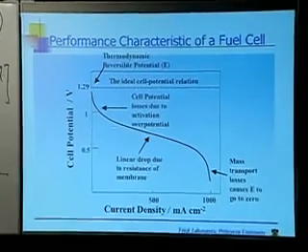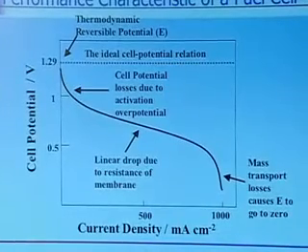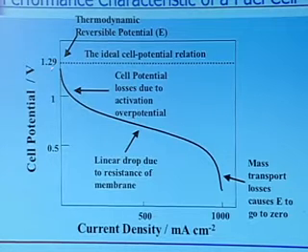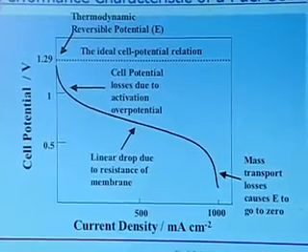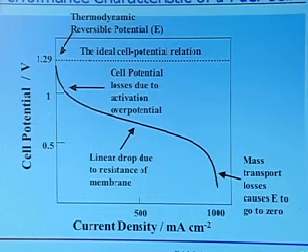And we run into a region now where we're limited by the resistance of the cell. Now, that is primarily the resistance of the Nafion, but there's also a fairly important resistive component from the Nafion electrode interface. Okay. I mentioned to you before that the charge transfer itself could be thought of as a resistance, but that resistance is up in this region here, in the Tafel region. I'm talking about the fact that unlike most electrochemical cells, I'm taking an electron, and a proton in this case, and moving it from a metal system into another solid state, not into a solution, but into this piece of Nafion. And so I have a resistance for that interface, an additional resistance for that interface.